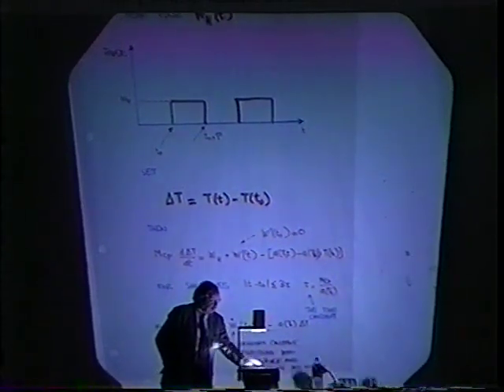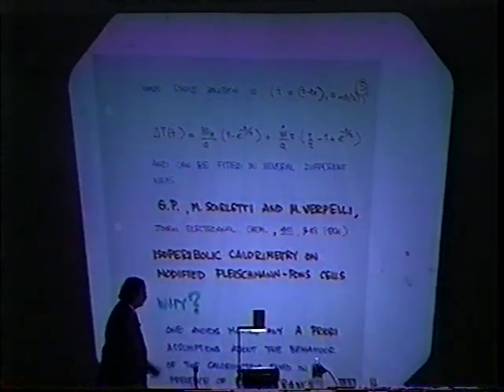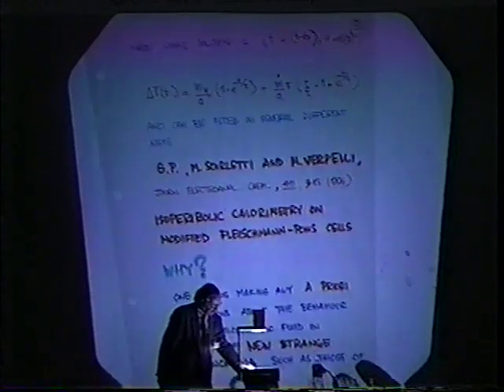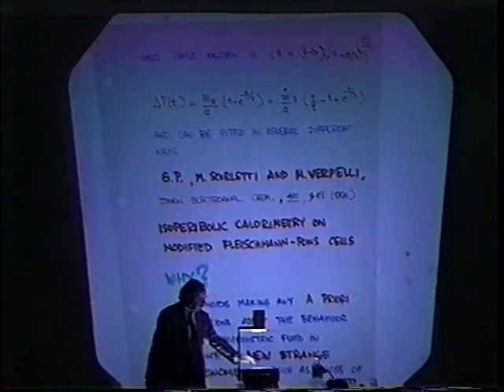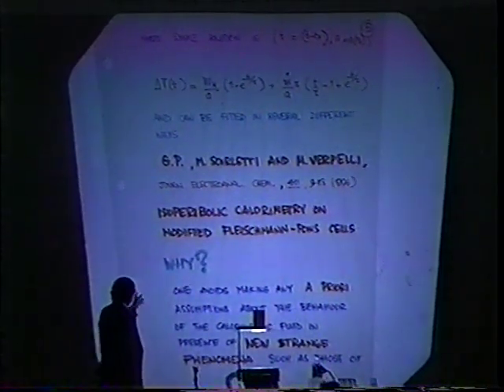Then the calorimetric equation around those points can be written in this way. You can put all the things you don't know about the fluctuations of the perturbations and so on into a linear term in this calorimetric equation, and then you have a simple solution for the variation of the temperature profile, which is this, valid when the time is very close to the discontinuity point. Note here that tau is a time constant of the calorimeter, and all these constants can be fitted in several different ways and easily determined from the transient. And this is what I show with two students of mine in this paper, which has just been published in the Journal of Electroanalytical Chemistry a few months ago.